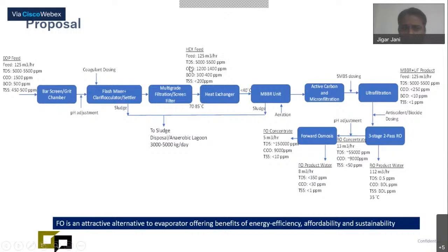Because the TDS is low, we are initially feeding it to the 3-stage RO system, wherein the permeate water will have a TDS of less than 0.5 ppm, and the RO reject, as you know, has a TDS of almost 55,000. There was no other technological option except sending it to a multi-effect evaporator. That's where we are trying to put in forward osmosis. Forward osmosis will get you almost 70, 75, 80% water recovery.